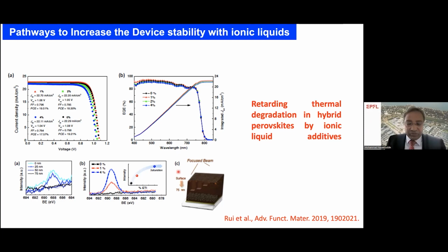Now we take our perovskite grain and, with the focused ion beam, we etch from top to bottom. Now what do you see on the top? We see at the top, at 0 nanometers, the fluorine binding energy at 688. And what do we see at 25 nanometers depth? We still see the fluorine binding energy of this material. And at 50 nanometers, we have nothing. So what this experimental data shows is that when we are forming these perovskite solar cells, this ionic liquid is floating and forming a shell on top of the perovskite grains. That's how it's protecting the perovskite from hygroscopic attack.